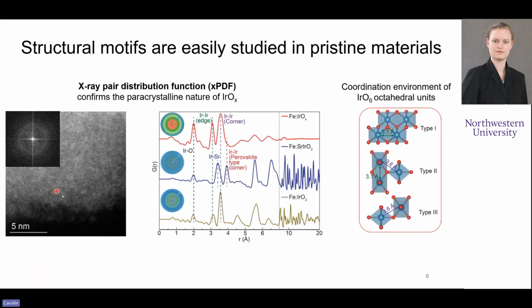So looking at the structural motifs that are present in the pristine catalyst materials, like the as-synthesized catalysts, we first see again this almost amorphous looking structure. There's a little bit of a feature in the FFT here. And our first method of taking a look at these was using the X-ray pair distribution function, XPDF, that we can calculate from X-ray scattering experiments.